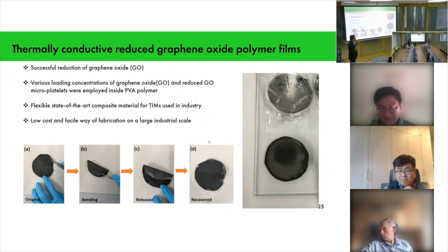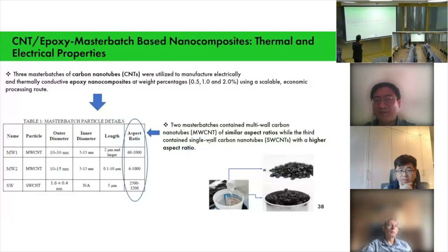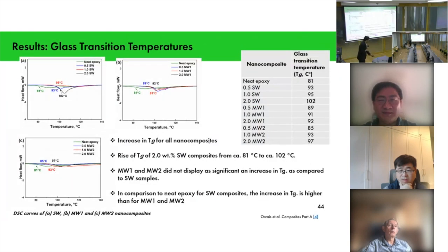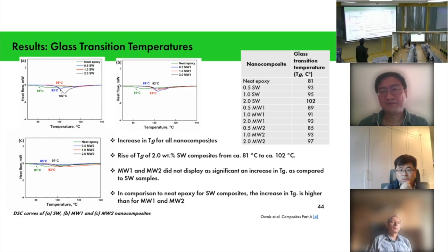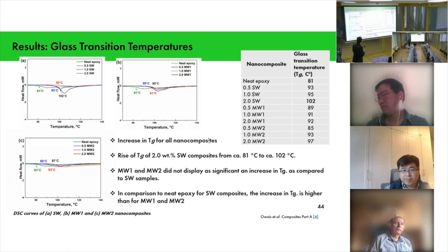So could you please comment about the glass transition temperature of carbon nanotube composite materials? You demonstrated that when you add some carbon nanotubes, the glass transition temperature goes up, right? Yeah, it goes up to 102. What is the reason behind it? Maybe it's due to the fact that the single wall carbon nanotubes have a high aspect ratio. So when you use homogeneous mixing, it inhibits the polymer segmental mobility of the system. With the high aspect ratio, the polymer will have an enhanced glass transition temperature compared to the multi-wall, which have a very short aspect ratio. So that can be a possible reason.